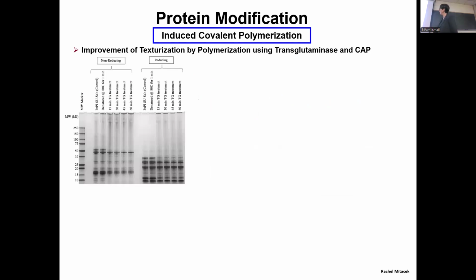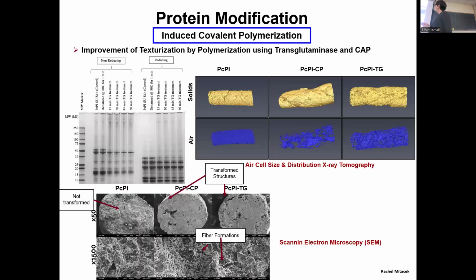So here we looked at transglutaminase under different conditions, and all of them produced large molecular weight soluble aggregates. Under reducing conditions, you still see the soluble aggregates because these were not disulfide interchange, these were covalent bonds formed by the transglutaminase reaction. In this study, we looked at pea protein, and we did cold plasma treatment and transglutaminase, and we texturized. So here, the texturization properties were enhanced for both cold plasma and transglutaminase.